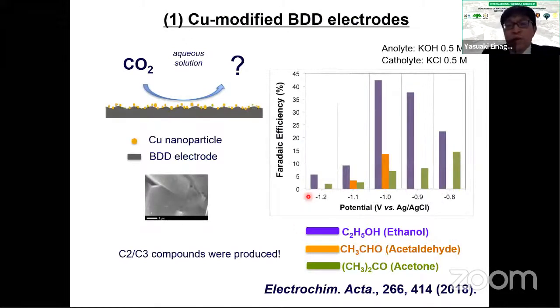So in order to produce other materials, we try to make metal-modified boron-doped diamond like this. This is a result of the copper-modified boron-doped diamond. This particle is copper on the boron-doped diamond surface. By using this one, acetaldehyde, ethanol, acetone, C2 and C3 compounds were produced. This is good because of the catalytic activity of the copper.